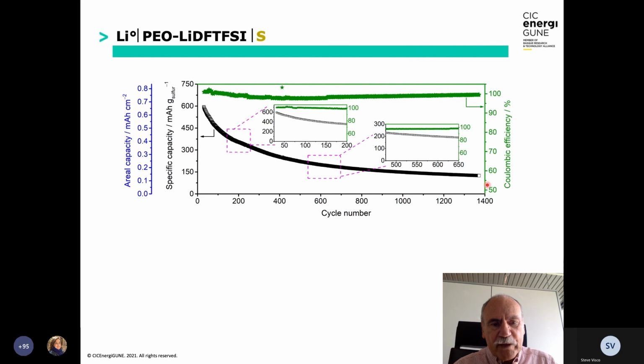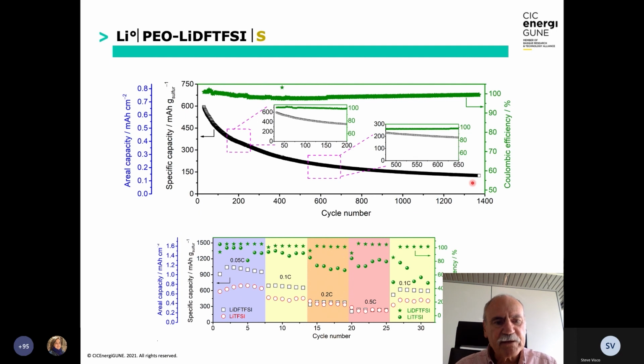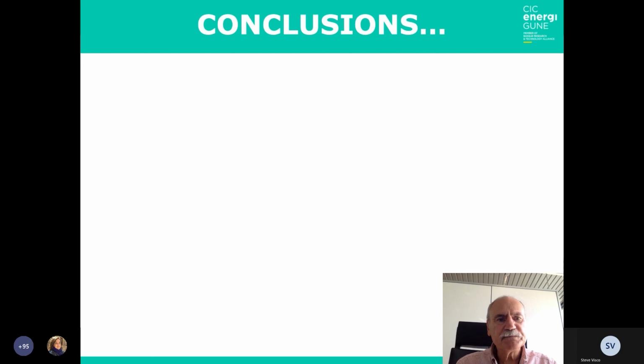This is, to our knowledge, the best result of a lithium-sulfur battery cycling without resorting to exotic electrolyte except for the new salt, without resorting to nanocarbon to trap the polysulfide. Simply the SEI of PEO-LiDFTFSI was sufficient. And as you can see, the C rate, the power of the battery, was still acceptable despite this SEI on the lithium. And I will go to conclusion now.